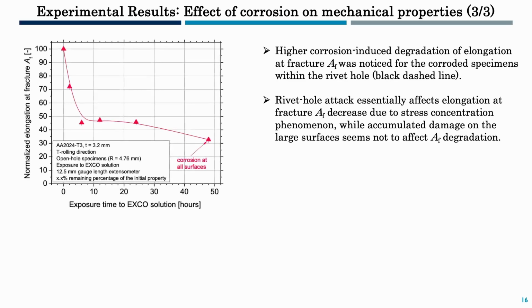And now moving to the most important property, elongation at fracture. It was noticed that higher corrosion-induced degradation is noticed for the corroded specimens where the rivet hole was exposed to corrosion. So it seems that the area inside the rivet hole essentially affects this property due to stress concentration phenomena, while accumulated damage on large surfaces seems not to play so significant a role, as we can see from the blue curve.